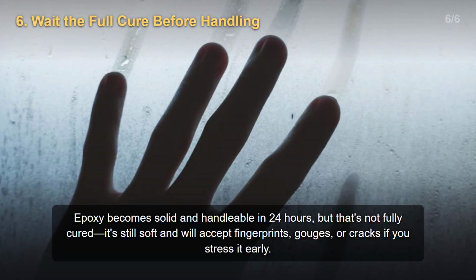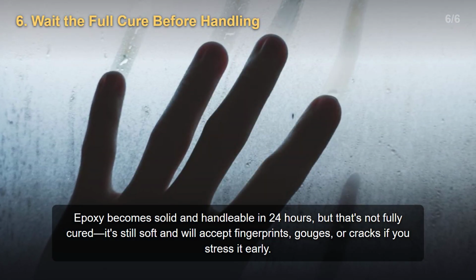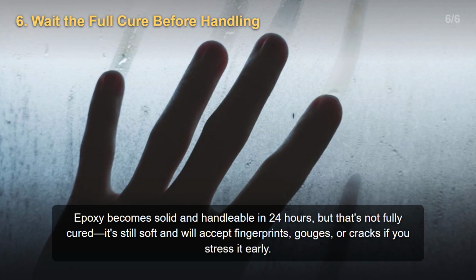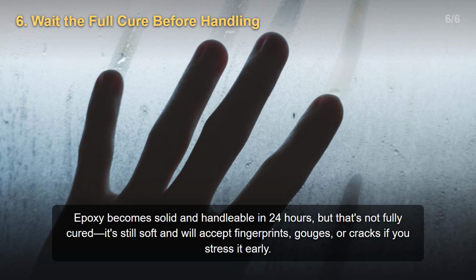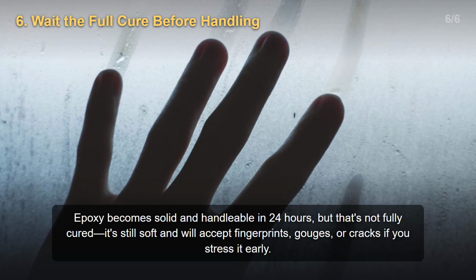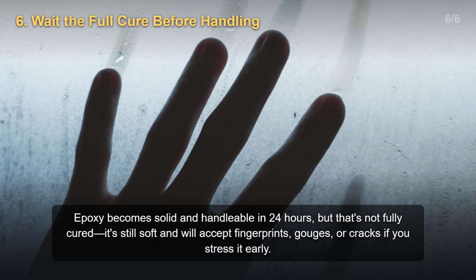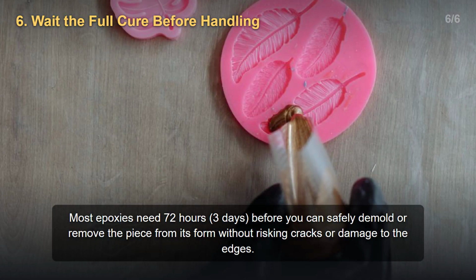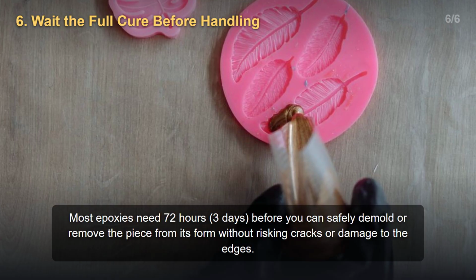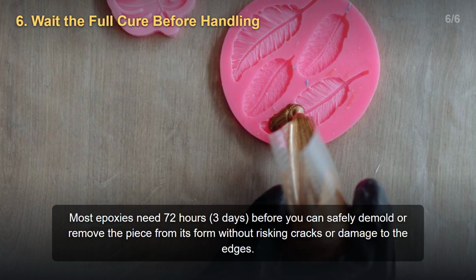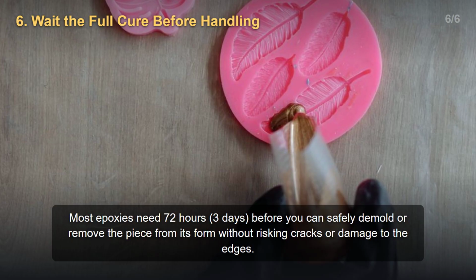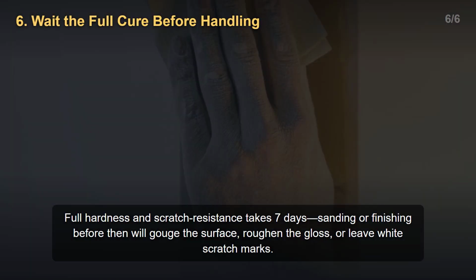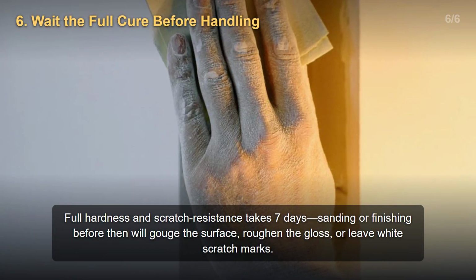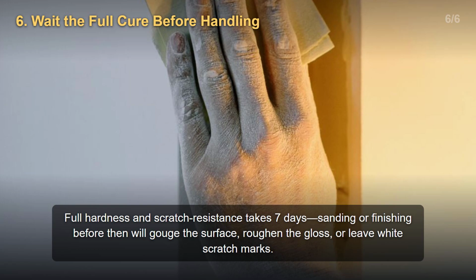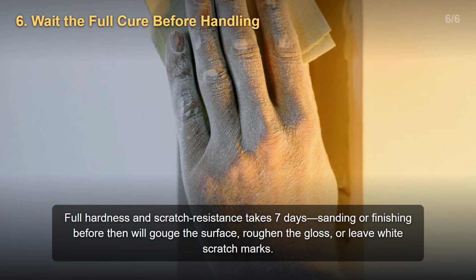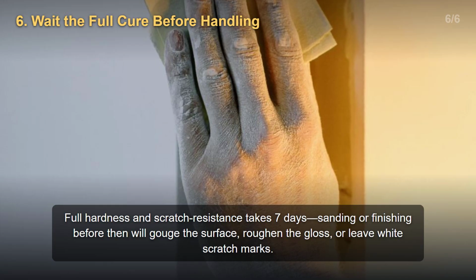Wait the full cure before handling. Epoxy becomes solid and handleable in 24 hours, but that's not fully cured. It's still soft and will accept fingerprints, gouges, or cracks if you stress it early. Most epoxies need 72 hours, 3 days, before you can safely demold or remove the piece from its form without risking cracks or damage to the edges. Full hardness and scratch resistance take 7 days. Sanding or finishing before then will gouge the surface, roughen the gloss, or leave white scratch marks.